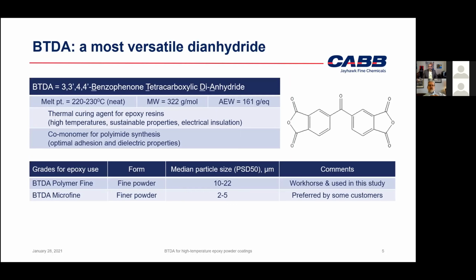One thing I want to mention to those that are familiar with powder coating processing technology, and as you probably know, our mixing step or our paint making step is compounding using a melt mix extruder. And as you can see here, the melt point of the material that we evaluated here is around 225 Celsius. It's very common to compound powder coatings closer to 100 to maybe 125 degrees Celsius.